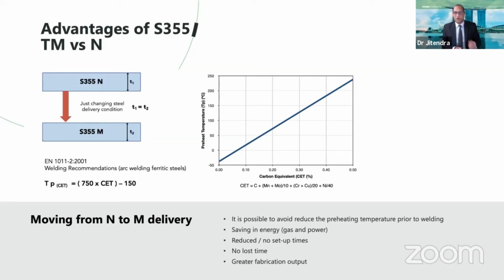as environmental when we go from a normalized plate to a microalloy plate, which is an M class delivery condition. And what this graph here shows is that by going to an M rolled steel, a thermomechanically rolled steel, and by using niobium, we're able to reduce the carbon equivalent. And by doing that, from a fabrication point of view, we may not need to apply any preheating conditions. And therefore that will save significantly on setup times, gas, energy, consumables, et cetera, in fabrication.